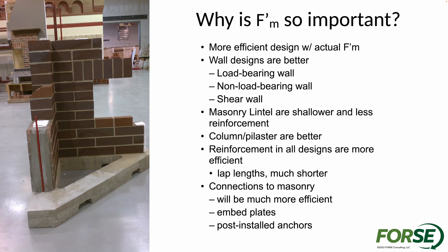Why is F'M so important? More efficient designs are going to be achieved with the actual F'M, so we don't want to use arbitrarily low values. We want to actually find out what the blocks are that are going to be used for our designs. Wall designs are going to be a lot better — both load-bearing and non-load-bearing walls. Shear walls are all going to be better with the actual F'M. We're going to have masonry lintels that are shallower and require less reinforcement. Columns and pilasters are going to be better. All of our designs are going to be more efficient — lap lengths are going to be shorter. And connections — masonry walls and columns that are used within buildings with many different materials connecting to those masonry elements — all of those connections are going to be a lot more efficient if we use the actual F'M.